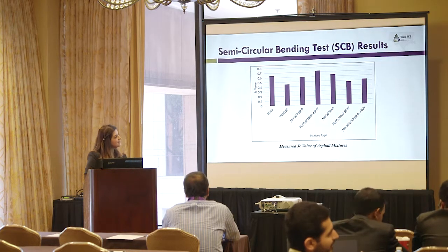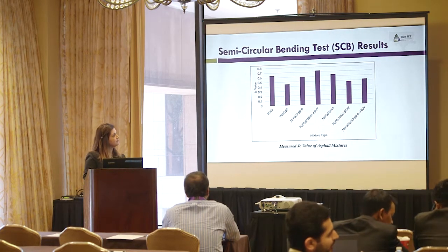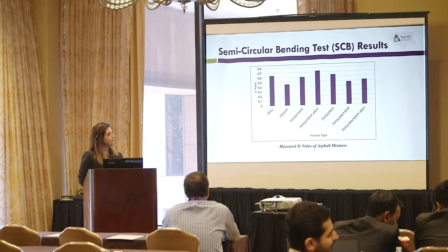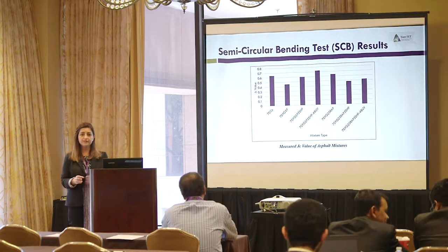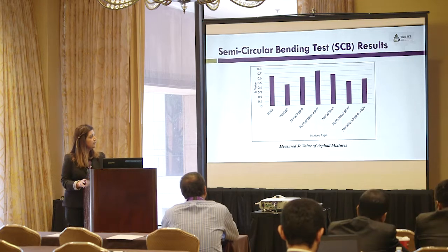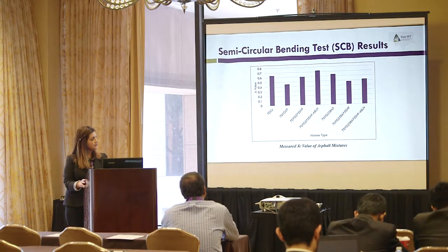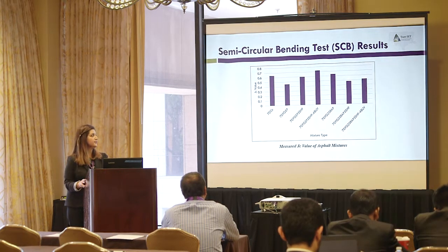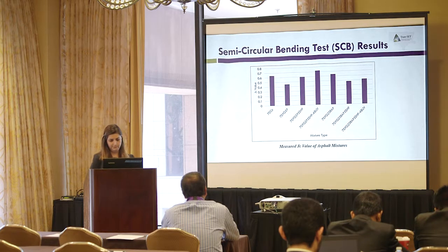But for the mixture containing RAP, when we added RAP, we almost have the same JC value. With adding self-healing polymer, the JC value decreased, but we were able to partially recover the JC value with UV light exposure. However, it's still lower than the JC value from the sample with only RAP.